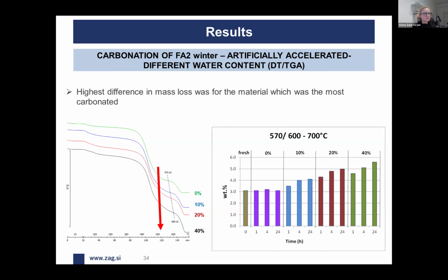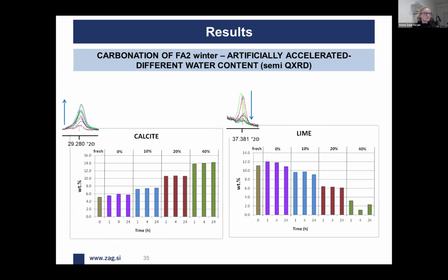This was confirmed by using the DTA-TGA methods, which is quite obvious here in the graph and also in the right figure. XRD, so phase composition, also nicely showed that in the case of samples with 40%, the highest percent of moisture content, the most intense peak of calcite is the highest, so the quantity is the highest. On the other side, of course, calcite was formed at the expense of lime and portlandite. And we can clearly see that the concentration of lime is decreasing with time and also with the water content.